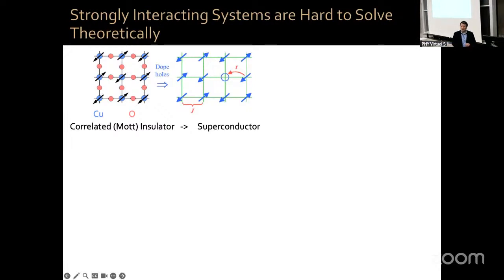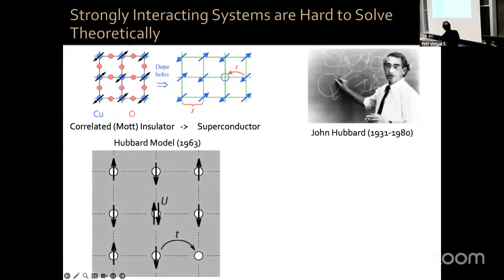Okay? Now, we believe that the simplest model that describes this type of behavior is given by the Hubbard model, in honor of John Hubbard, where there are only 2 parameters in the system. The energy penalty U to doubly occupy a site, and the hopping energy, the kinetic energy, t, between an occupied and an empty site. And despite the apparent simplicity of this model, these 2 parameters, and you have a whole bunch of electrons in this lattice, we do not know how to solve it exactly, theoretically.